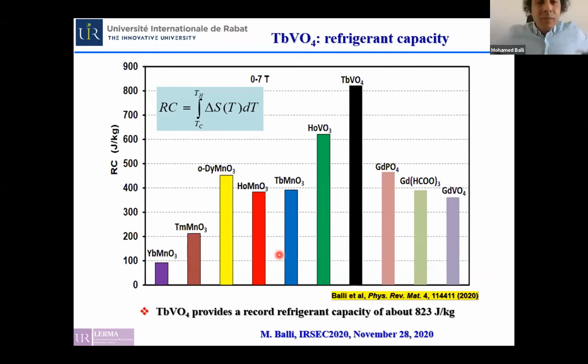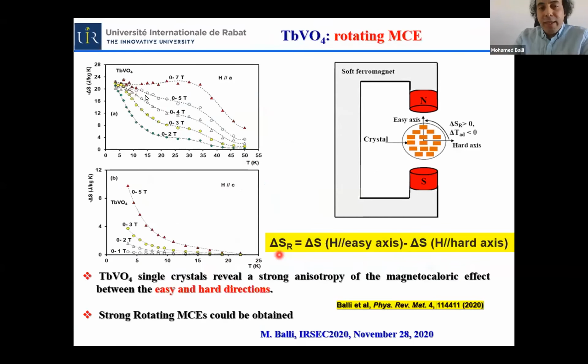Thanks, Professor Zaz. So this refrigerant capacity is very important because it takes into account both the magnetocaloric effect in addition to the working temperature range. In other words, the refrigerant capacity measures the energy that can be transferred in an AMR cycle between the hot and cold ends. Also, as expected, you can see here that the material presents a strong anisotropy of the magnetocaloric effect.